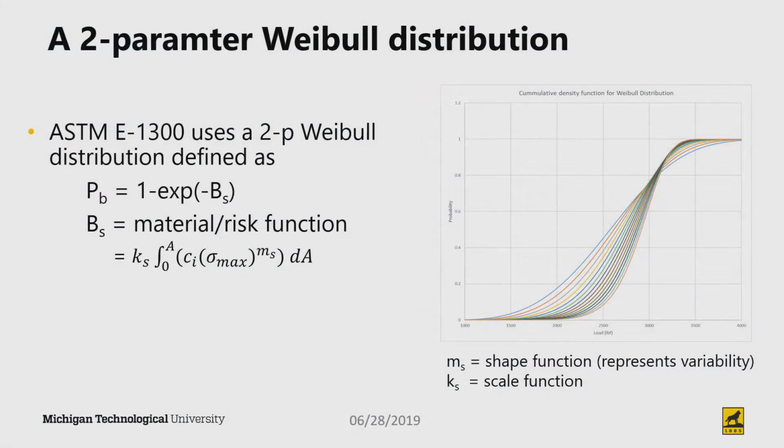This is why the model is nice, because we're not assuming that the glass is going to fail at the location of the single largest stress. The critical flaw could be somewhere other than that maximum stress, and because we're taking the area into account, we can address that.